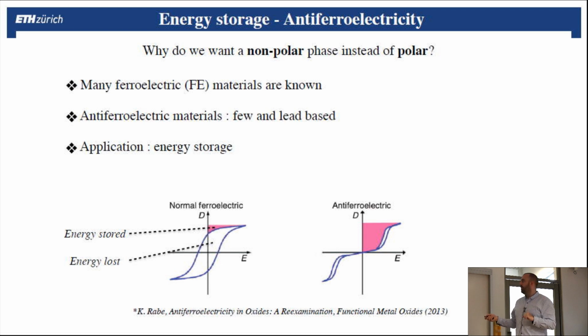It will result in no net polarization, but the interest is that if you see here this hysteresis loop, when one applies the electric field, you induce polarization. And if your material is a normal ferroelectric material, then the energy that you will lose will be proportional to the surface here, but the energy that you can store will be proportional to this purple surface. For an antiferroelectric, it would be in this shape. So it will be a linear response first, and then you will recover a ferroelectric behavior like here.